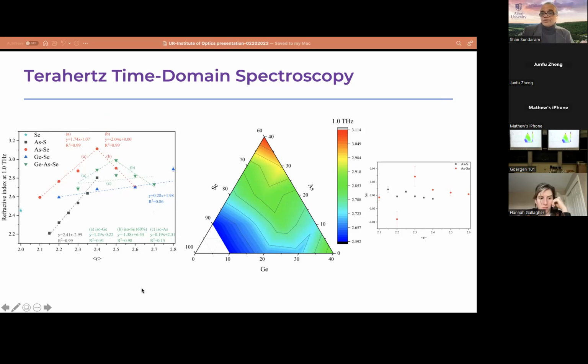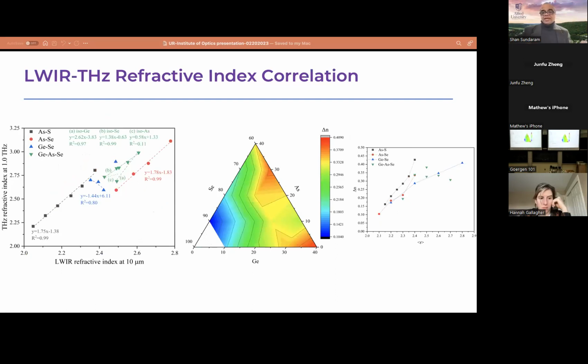We are also showing you how for various arsenic sulfide and selenide compositions, when you change the average coordination number of these glasses, how the refractive index delta n changes as a function of composition. So that gives you also an idea how I can tailor the composition in this triangle by mixing and get the composition I want.